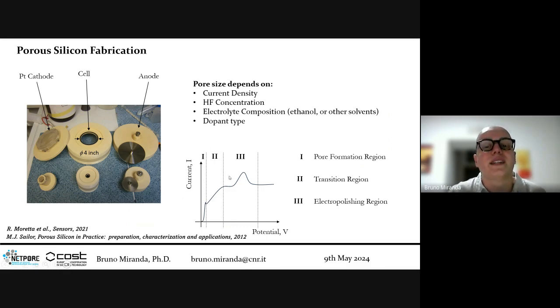This curve is generally made to characterize your silicon wafer. You will have an increase in current according to the applied voltage. You can obtain this IV graph in which you have the first region of pore formation. Then if you increase the current and potential, there is a transition region with no pore formation, but also no electropolishing. Finally, there is a third region where electropolishing occurs.